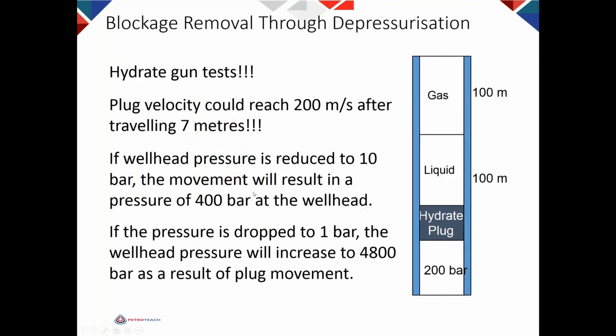This is some tests that people have done. Imagine you have a wellbore. The pressure at the bottom is 200 bar. You have a hydrate blockage. You have 100 meter of liquid water, and you have 100 meter of gas. So you can see that if we reduce the pressure from 200 bar, here, reduce the gas phase pressure to 10 bar.